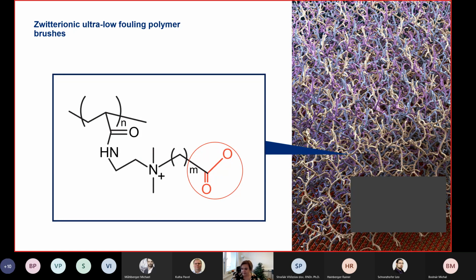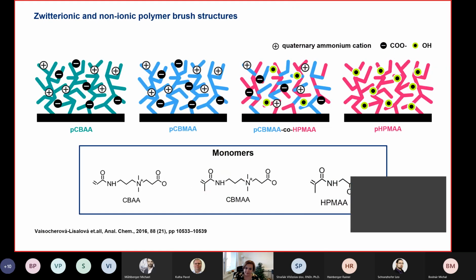The key is the chemical structure. The chemical structure of monomers, which are present in the whole architecture of the polymer brush. We are typically using zwitterionic moieties, which are somehow incorporated into the structure, and we are mostly playing with the carboxybetaine, which is very interesting because it's a molecule which is hydrophilic and also contains a carboxylic group, which can be used as a functional group for attachment of biomolecules.